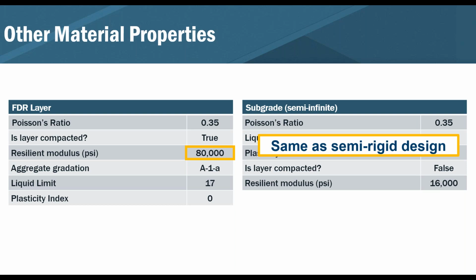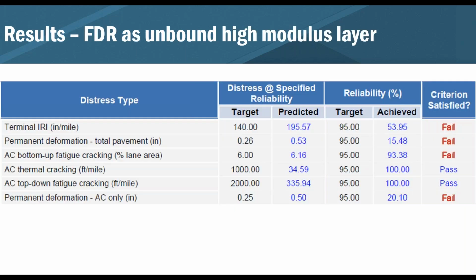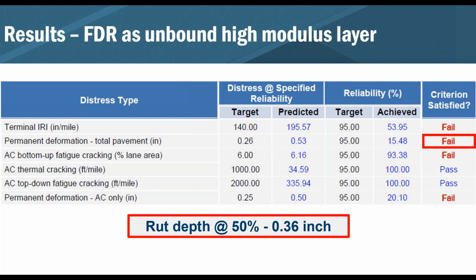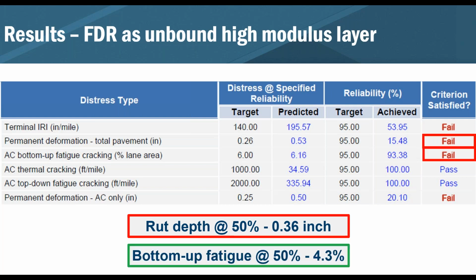The results from that analysis showed that the predicted IRI actually dropped quite a bit, but certainly the permanent deformation is still failing. It's actually the same as it was previously at 95%, but at 50% reliability, it's a little higher at 0.36. And certainly the bottom-up fatigue cracking is failing, even though it's barely failing: 6.1 or 6.2% predicted versus the 6% target. But at 50% reliability, it does pass with only 4.3% fatigue cracking.